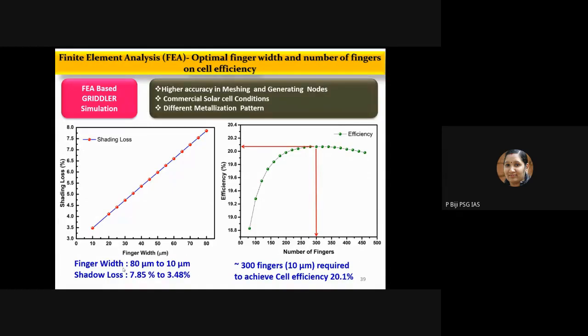From this we can understand that as you decrease the finger width, the shading loss decreases. That is quite obvious. We also tried to do the efficiency calculation in terms of the number of fingers. If you reduce the finger width, you need to increase the number of fingers. For 10 micrometer fingers, we found that almost 300 fingers are required to achieve an efficiency of 20.1. But unfortunately, if you increase the number of fingers like this, 300 lines of 10 micrometer, there are processing challenges, and you can expect that several finger breaks may occur. So you have to avoid that kind of reduced dimension.